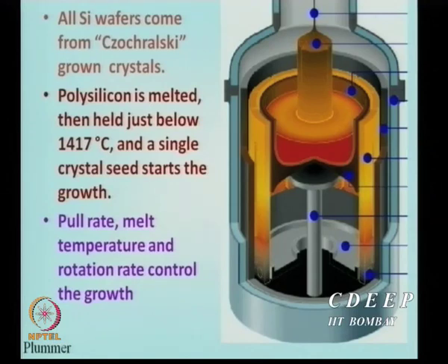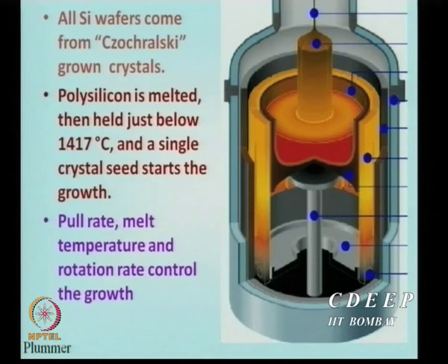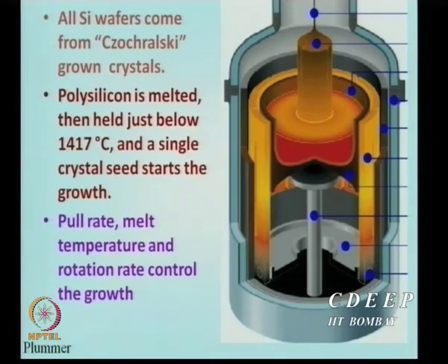Please remember the concern here. If you see the tip where the single crystal seed was, the solid which actually picks up from the melt has a much larger diameter because of the curvature. Depending on the kind of crystal size you initially start with and the kind of initial touch, the size of the rod is different. So how much you allow it to grow along this direction before starting to pull determines the crystal diameter. There are tricks in doing this — it is not very easy for outsiders but people who do it routinely manage it.